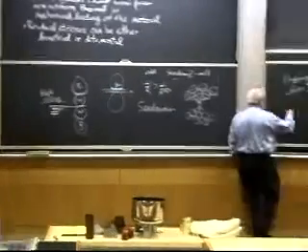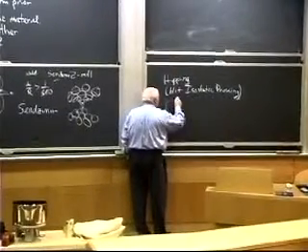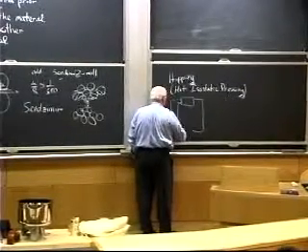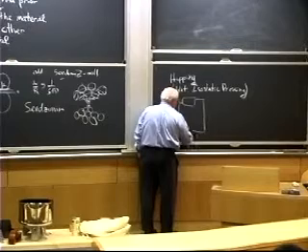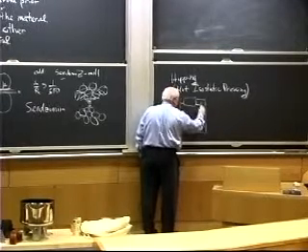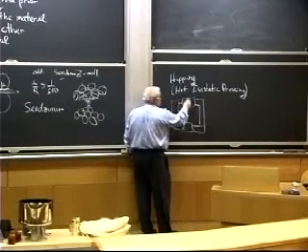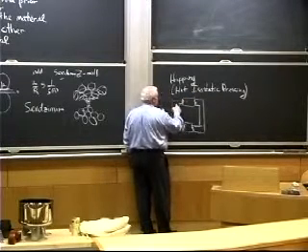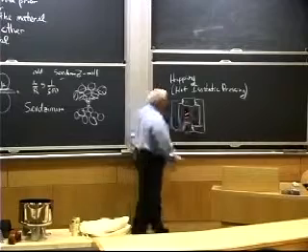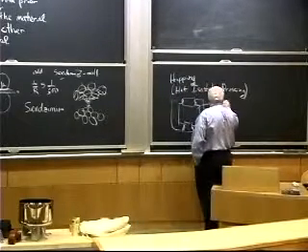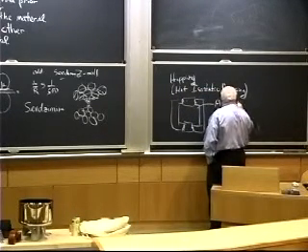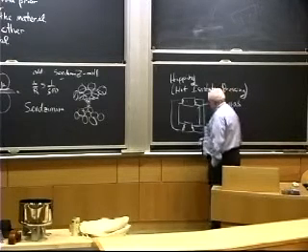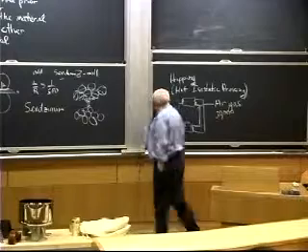But a hot isostatic press is nothing more than a pressure vessel, a big pressure vessel, that will take, well, the one we had would take 30,000 psi. So this is your pressure vessel. You'll have a top closure, typically threaded in, screwed in, and then you have big, heavy, thick walls. And you can put argon gas in here and typically go up to around 30,000 psi. There are some that go to 45,000. There are some that only go to 15,000 psi.